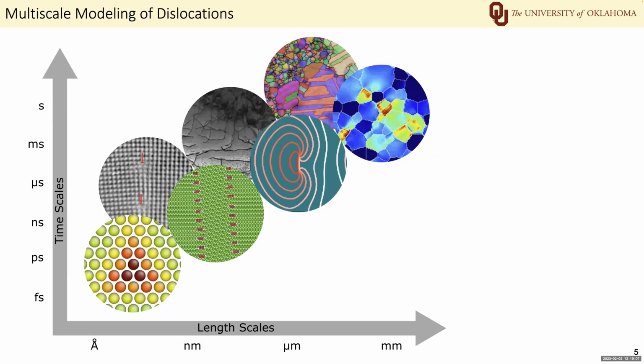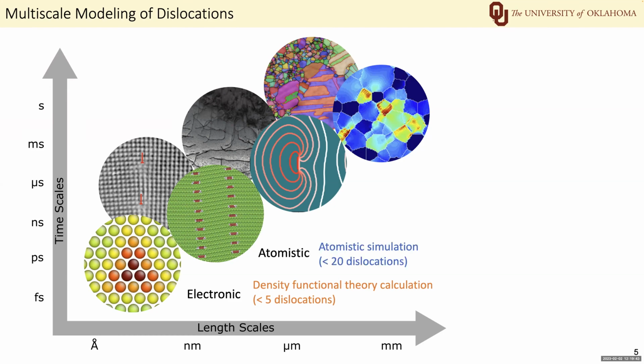So materials are multi-scale systems. Their structure and behavior span over multiple length and time scales. But at each scale, there is at least one method to model the dislocation. At the electronic scale, we can use the density functional theory calculation. The simulation cell usually contains less than 5 dislocations. At the atomistic scale, we can use the atomistic simulation. The simulation cell usually contains less than 20 dislocations.